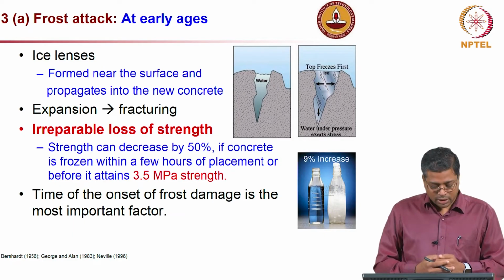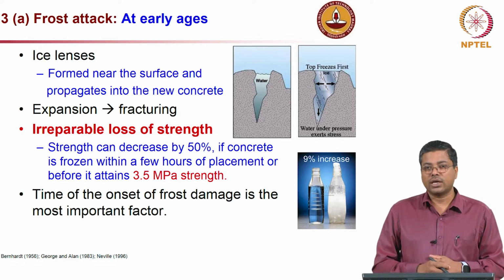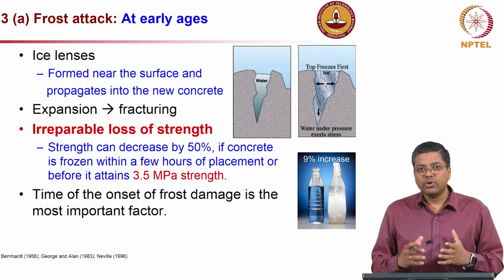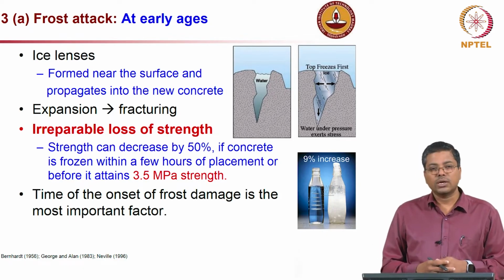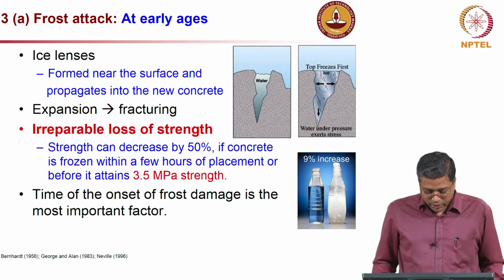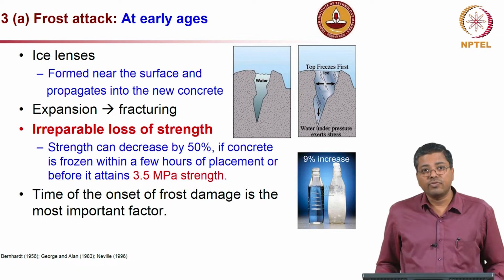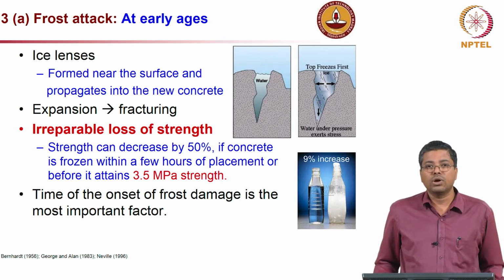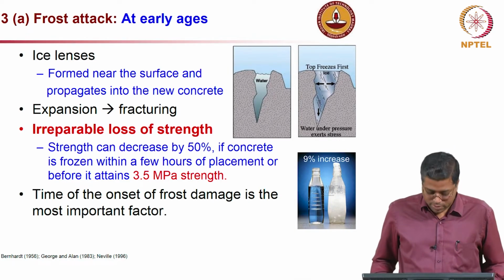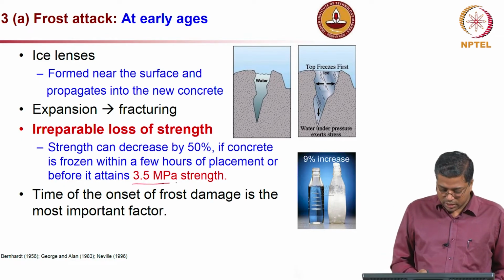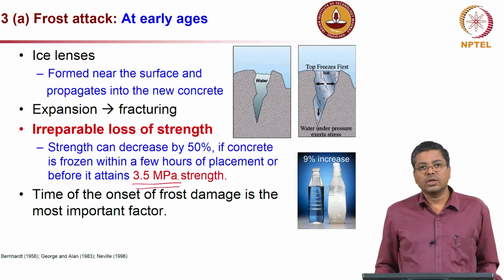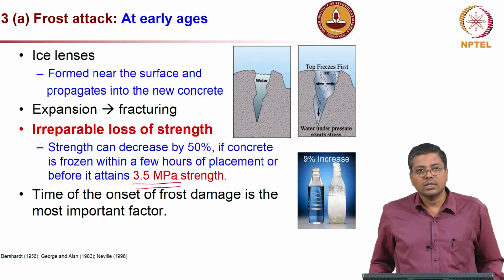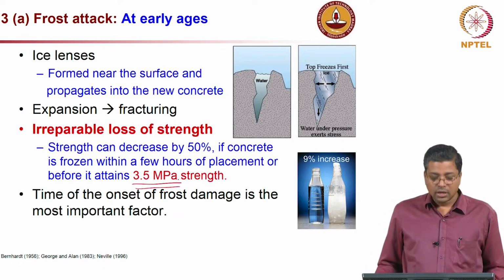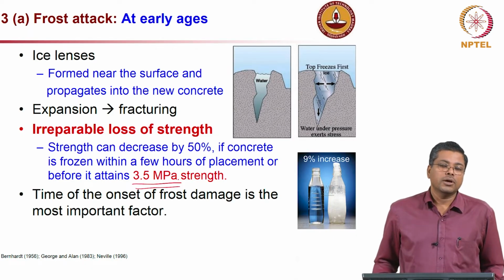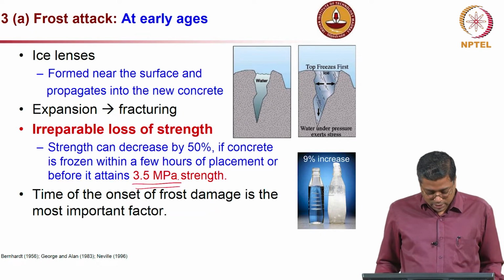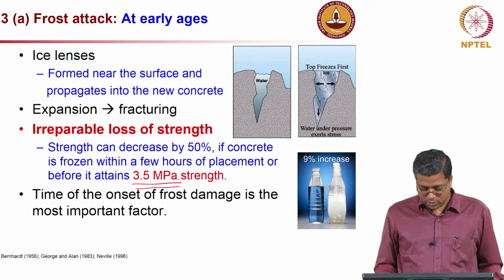And what it ends up in is an irreparable loss of strength, which is very important, because if you do not get that strength, you cannot really gain it at a later stage. The strength can decrease by about 50% if the concrete is frozen within the first few hours of placement or before it attains 3.5 MPa strength. This 3.5 MPa strength requirement is given in most of the codes. So, in cold weather concreting, we have to first ensure that the concrete gets 3.5 MPa, then protect that concrete further by ensuring adequate moisture and temperature. We will cover that later, but remember this number 3.5 MPa, it is very important.